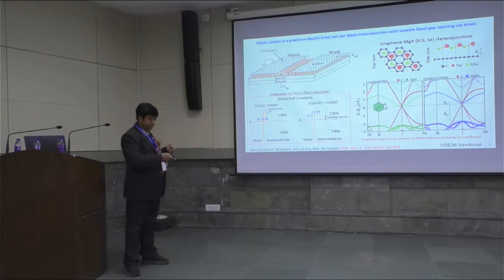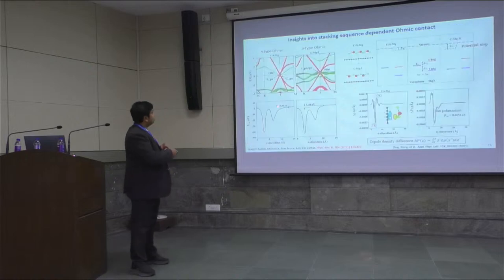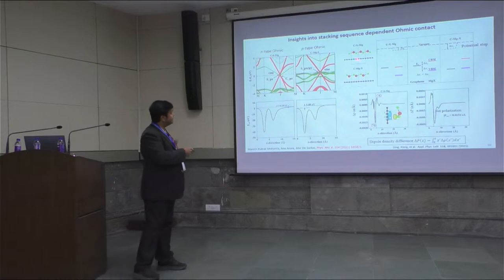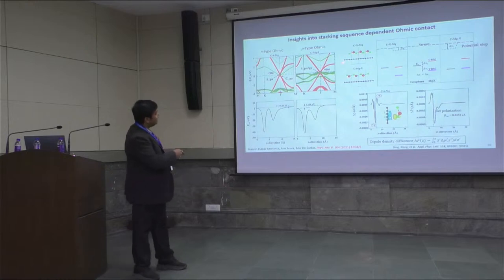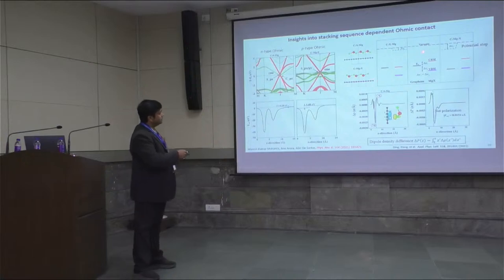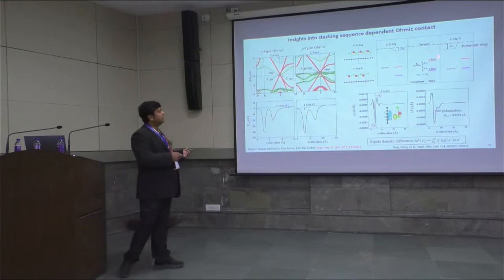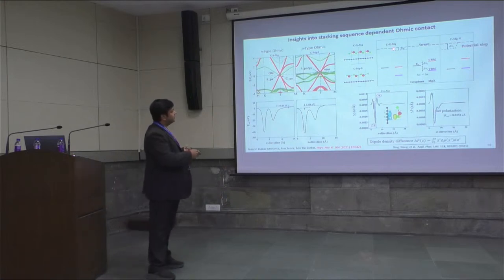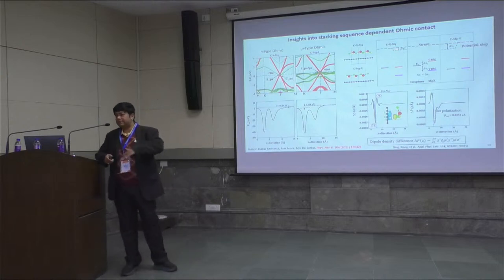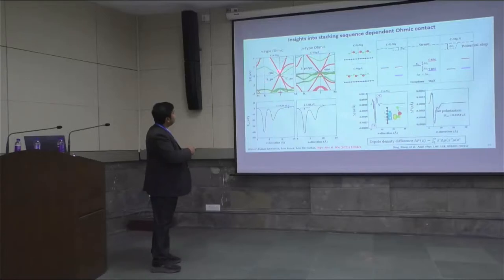That means the Schottky barrier is zero. Now, the nature of the ohmic contact, whether it is an N-type or a P-type ohmic contact, is found to be sensitive to the stacking sequence, whether the chalcogen atoms face graphene or the magnesium atoms face graphene, because this is the band alignment on the absolute vacuum scale. When the interface is formed, the potential step is different. It varies from one to the other, because the interfacial polarization varies from one stacking sequence to the other. So in the end, we get an N-type ohmic contact in this stacking sequence and a P-type in this case.